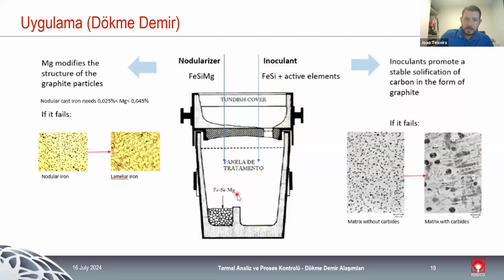And the stable solidification of carbon is basically allowing carbon to transform into graphite and not into carbides. Most of the cases where we find carbides in the cast, they are because the inoculation process failed at some point. Either it was not enough to allow the transformation of carbon into graphite, or it wasn't strong enough, so we need a stronger active element like lanthanum or bismuth, or we have problems with the design of the gating system, and there are some areas of the cast that are isolated and they don't receive enough liquid metal to transform the carbon into graphite.